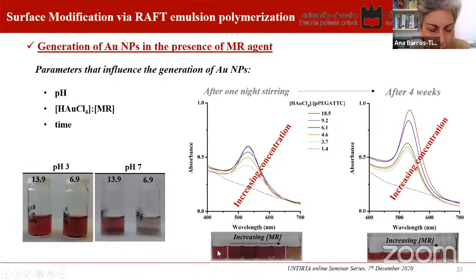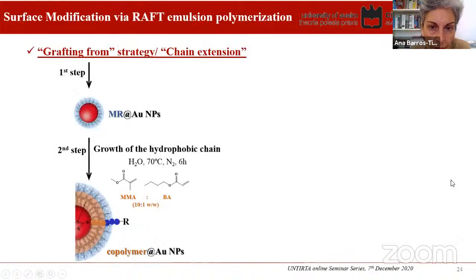So these are all too many parameters to try to control if we want to make some sort of biosensor. This is not really terribly practical. That's when we definitely moved to the grafting from approach strategy, or chain extension. This involves two steps. The first step where we prepare the macro RAFT adsorbed onto the gold nanoparticles, and the second step when the growth of the hydrophobic chain takes place.